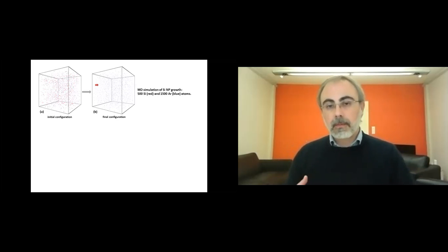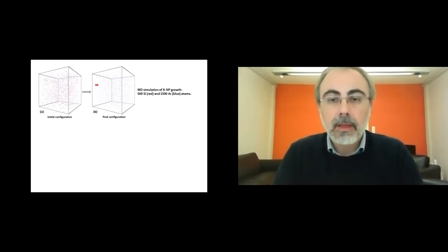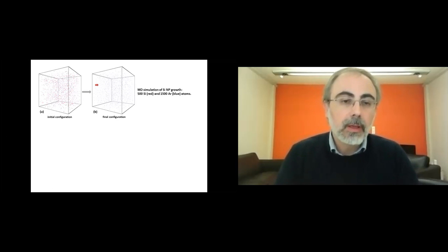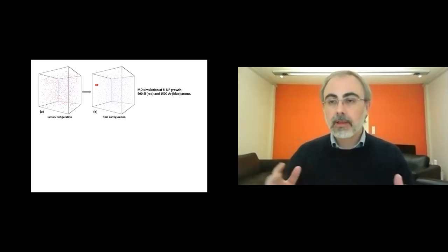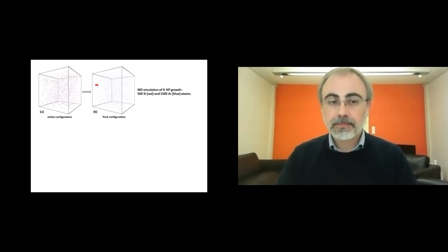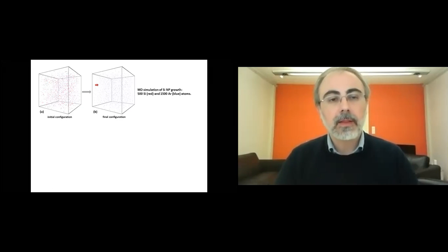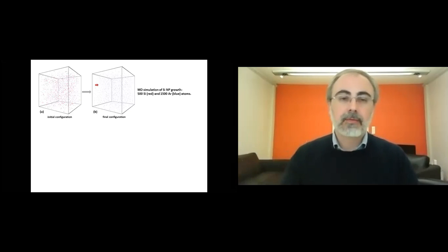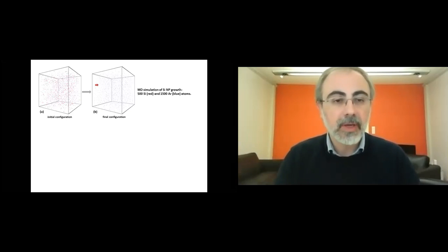When we start the simulation, the sputtered atoms are supposed to be hotter, more energetic, so we start with a high temperature for them. And we have introduced an idea that the argon gas atoms are rethermalized every time they go past the periodic boundaries of the box.